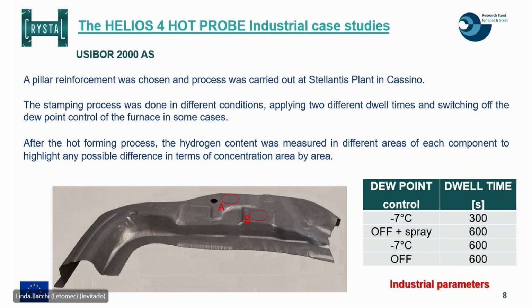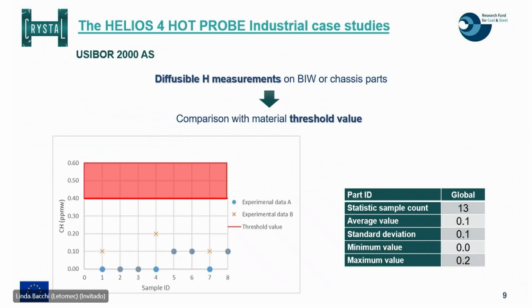After this hot stamping, we realized a series of diffusible hydrogen measurements by means of the Helios 4 hot probe. In this case, we identified a couple of areas, A and B, on the component. Here you find the statistical evaluation of what we found in this experimental campaign. We found very low hydrogen content in almost all the components and in both areas analyzed. The maximum value that we found was 0.2, and the average value was 0.1. If we compare to the literature value for the critical threshold for hydrogen embrittlement of this specific material, represented by the red line, all of the measurements that were performed were much lower.